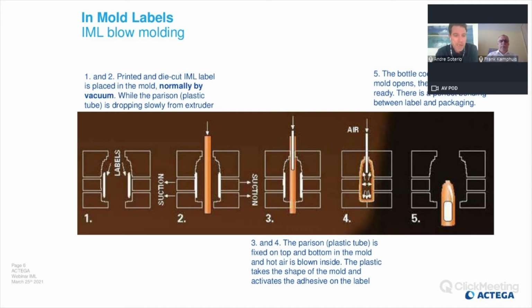At the same time, there is a kind of molten plastic tube, what we call a parison, coming down from the extruder. This is just like a small tube, and the mold will close, holding the parison on top and bottom, and the machine will blow hot air into this tube, and the tube will take the form of the mold. As the tube is still hot, it will touch the back side of the label. The label will melt together with the bottle. The mold is cooled down, and we have the final product.